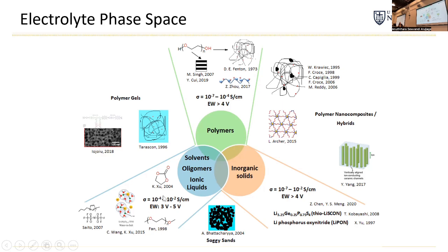Our current commercialized lithium-ion systems, of course, use liquid electrolyte, but in the 1990s, Bellcore commercialized what they called a plastic lithium-ion cell, which actually contained a sort of polymer gel electrolyte. But that didn't maintain as much market share as our current system, where we have this inert microporous separator. And then within the polymers case, there's a company now, Blue Solutions, in France, where they have all solid polymer batteries that are being used for transportation. But of course, the conductivity is lower in those electrolytes, so they have to operate them at much elevated temperatures.